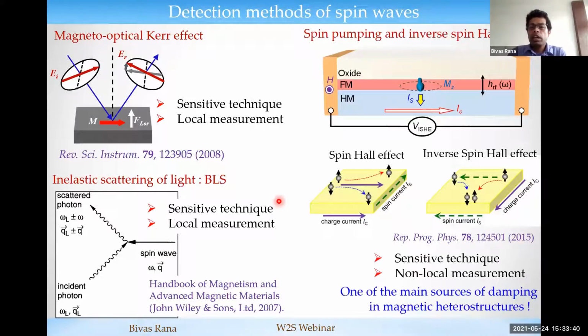And the third technique is the electrical technique. So basically, consider a heterostructure made of a heavy metal and a ferromagnetic layer on top of that, and you excite the ferromagnetic resonance in here, and that creates a spin current. That is the means of transferring angular momentum from localized magnetic spin to conduction electrons, and by virtue of the inverse spin Hall effect, you can convert that to a charge current, and then you measure the potential drop across this heterostructure, and that's how you can measure the spin wave in the system. And this spin pumping and inverse spin Hall effect is one of the main sources of damping in this heterostructure, which I'll be talking about shortly.